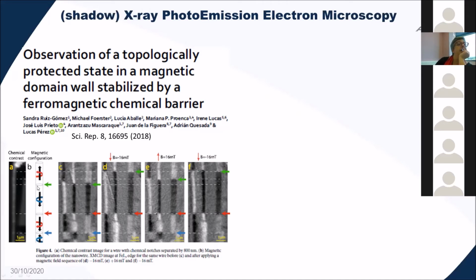The walls where chirality is not switching have a reversible displacement with small magnetic fields, always pinning at these notches, whereas the others require a much higher magnetic field to be depinned, where the chirality must switch, okay? So this is something one can only understand knowing the magnetization of surface and core of the wire.